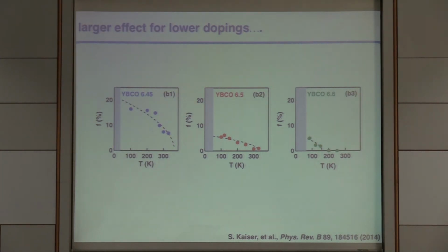Eugene, you were asking something. So how long does this transient superconductivity last? Is it also picosecond? Right, depends. In the 1/8 compound, for example, in the LESCO, where you have this real sort of stripe melting and such, it can last many, say more than a nanosecond at low temperatures. In this case, instead, it lasts anywhere between 3 and 7 picoseconds, depending how you fit the data. Let's say more 3 than 7, probably.